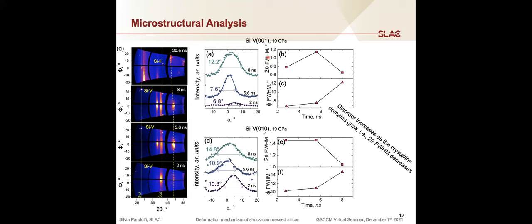And this happens as the full width at maximum along theta, so along the scattering angle, decreases. So it seems that there is a correlation between the growth of the crystalline domain, which is indicated by the decrease of this 2 theta full width at maximum, with the increase of the disorder in the sample. And what's interesting to notice is that we do have at first the phase transition, which appears to happen with a very strong preferential orientation, and then this mosaicity starts and disorder starts developing.